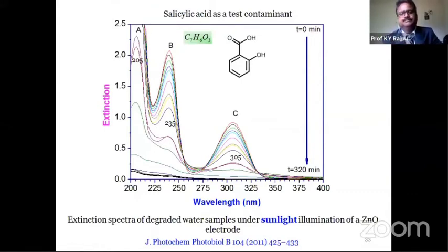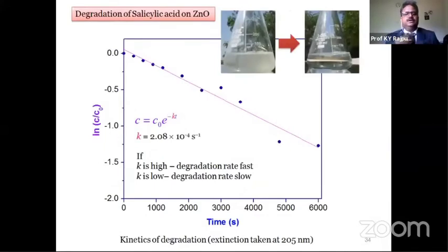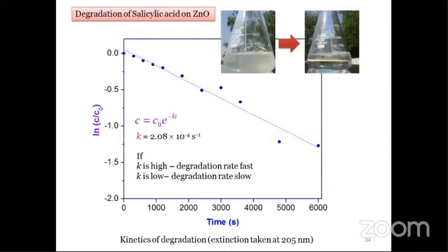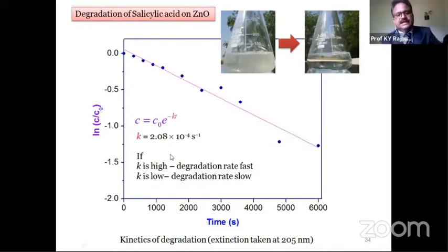If you plot the logarithm of the relative extinction coefficient with respect to time, it is seen that it continuously decreases, and for the reaction constant K, if it is high, the degradation rate is fast, and if it is low, the degradation rate is low.